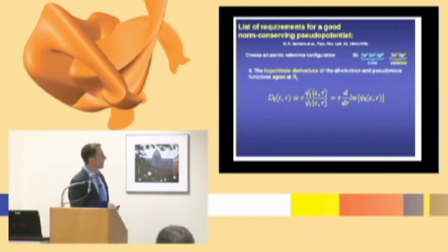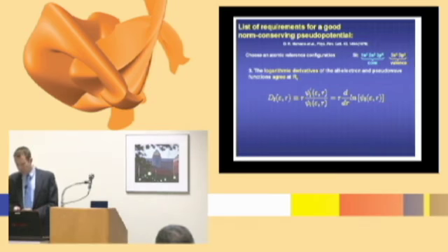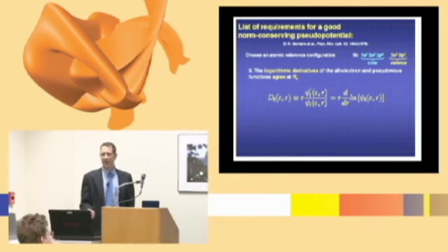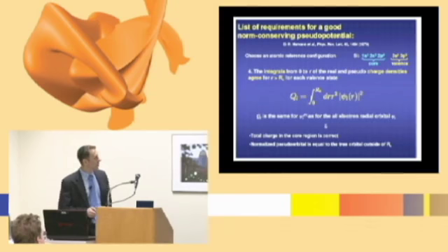Third, and this is something people tend not to look at, but you should, is that you should check that the logarithmic derivatives of the all-electron and pseudo-wave functions agree at the cutoff. So they don't have to agree, but they should agree. They need to agree in order to get so-called transferability, which means they don't just work for recomputing the atom, but they also work when you apply them in your crystal.